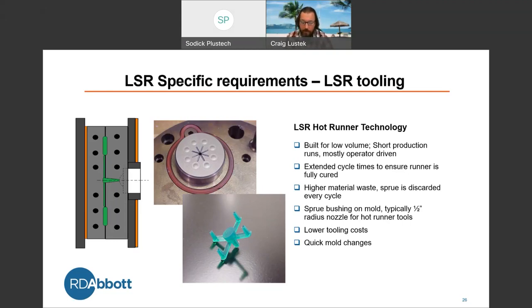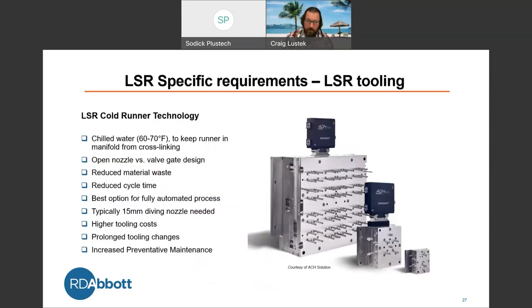Mostly operator driven. Now, mind, there are options out there where it can be higher volume and you can automate it. Cycle times tend to be longer because you can see, for example, in this slide, that runner is a little thicker. So we need to make sure that we're curing that runner up properly. So you do have a higher material waste. That runner is going to be discarded every cycle. Again, I mentioned the sprue bushing is typically half inch radius on the hot runner tools, lower tooling costs, quick mold changes. Versus we're looking at cold runner technology. Again, chilled water to keep the manifold from cross-linking or vulcanizing, curing up.